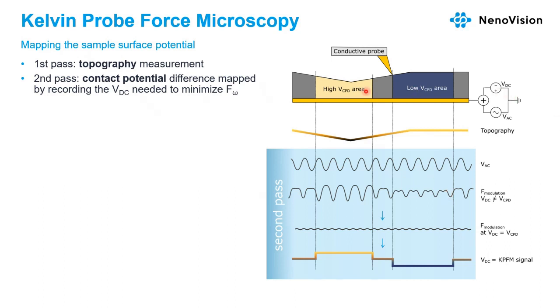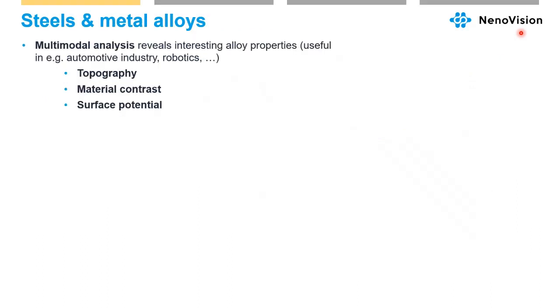In the first pass, we measure the topography. And then in the second pass, we follow the topography and minimize the contact potential difference in each point of the map by adding the DC voltage. And this DC voltage is actually the KPFM signal. So we see that brighter is a higher potential, darker is the lower potential area. I have an example from steels and metal alloys.